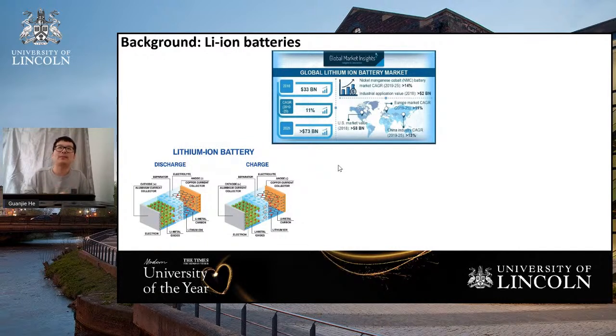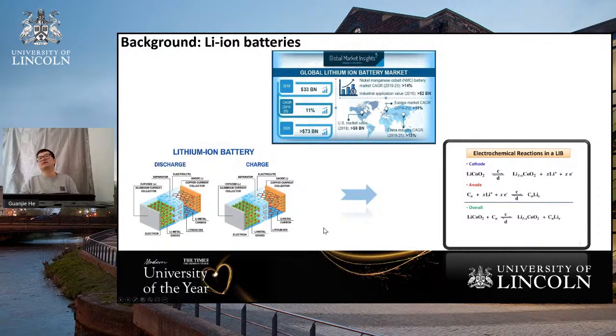If we look at the energy storage mechanism of lithium-ion batteries, it is quite simple, to be honest. Let's use a simple cathode material, lithium cobalt oxide, as an example. During the charge, lithium can deintercalate from the lithium cobalt oxide into the electrolyte. As for the anode material, we usually use graphite or lithium metal, and during the charge process, the lithium intercalates into the graphite. For the discharge process, the reaction is reversible. So the overall reaction during charge and discharge is just lithium intercalating or deintercalating into the electrode materials. But lithium batteries have some drawbacks, and also a huge advantage. Let me present them to you now.